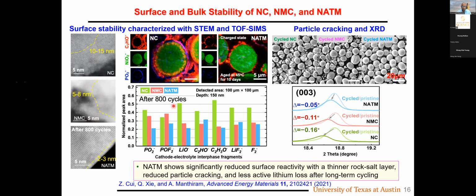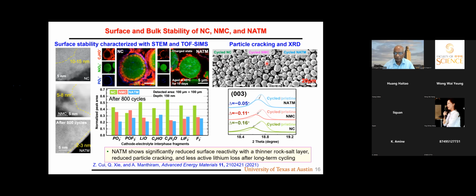So it's all consistent. If you look at the crack, NC has more crack, NMC has less, and NaTm has obviously the least amount of crack. More importantly, after 800 cycles, if you look at the X-ray diffraction pattern, particularly this 003 peak, the faint curve means initial, the thick curve means for each material after 800 cycles.